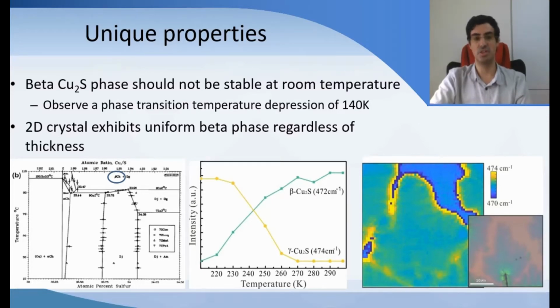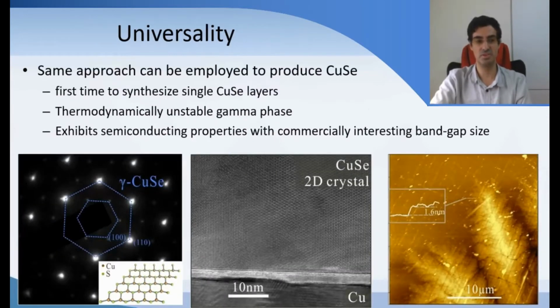This is not limited to sulfurization. We've played with different materials, iron sulfide and nickel sulfide, as well as copper selenide. And so copper selenide is forming, again, a normally unstable gamma CuSe, and it's forming atomic interfaces. But interestingly, because the sulfur is smaller than selenium, so it diffuses faster, we can actually get selenium crystals that are down to a single monolayer. So we're measuring, in the presence of both graphene and a water layer, about 1.6 nanometers. So extrapolating from there, we're getting that CuSe is a single layer if we're growing it short enough.